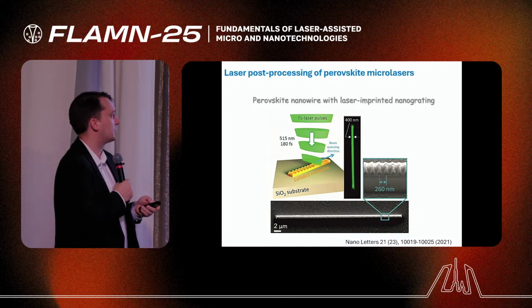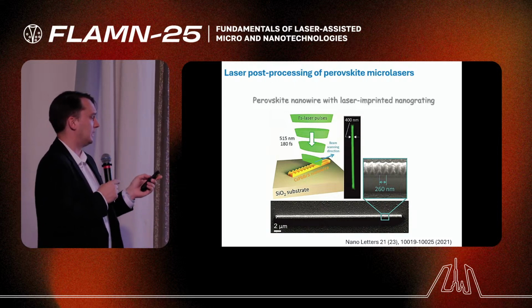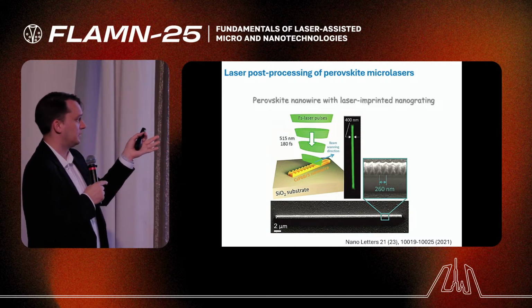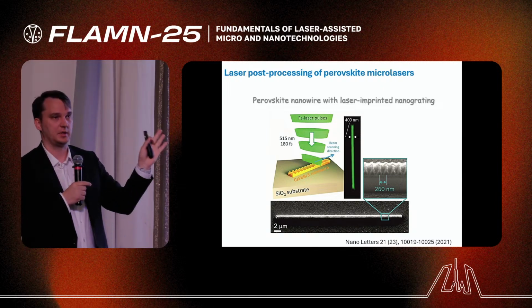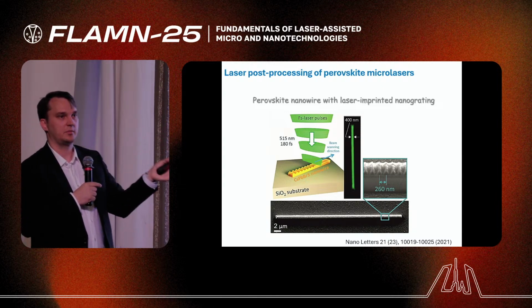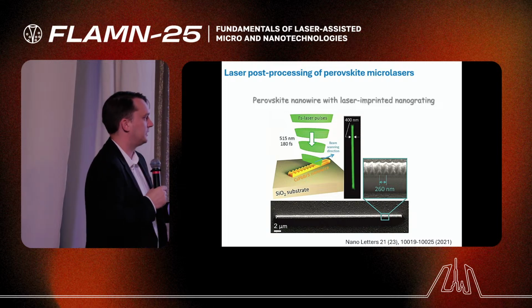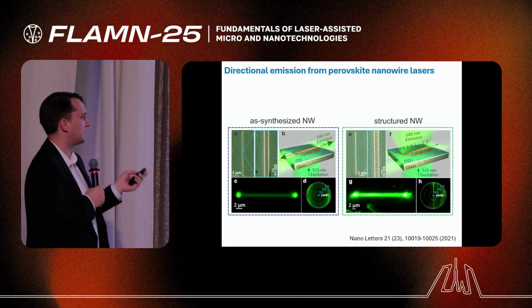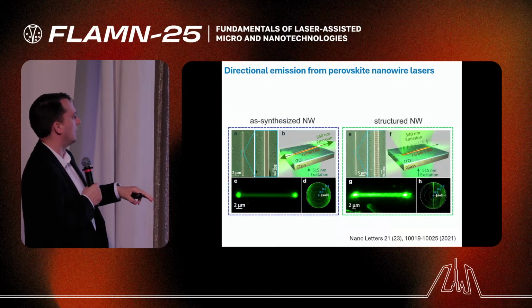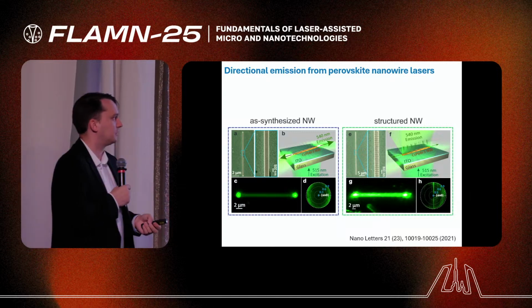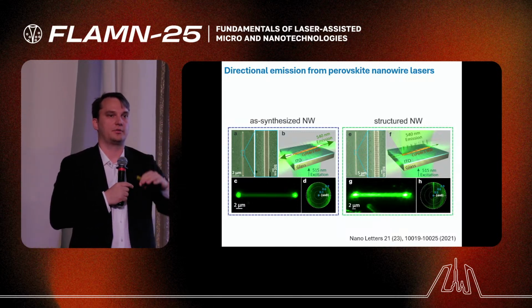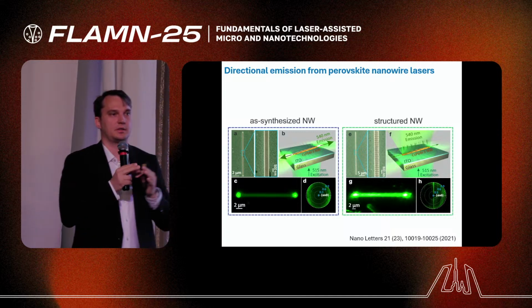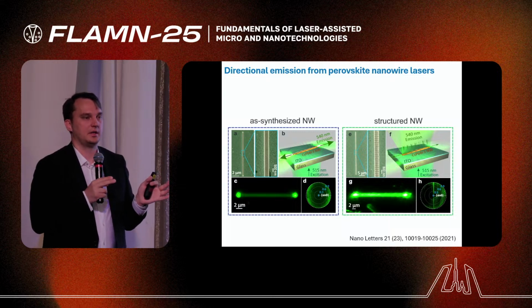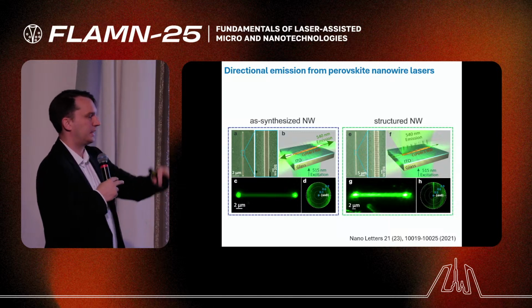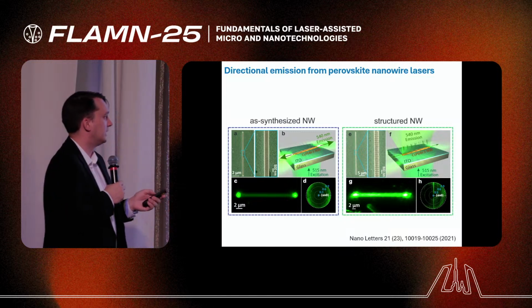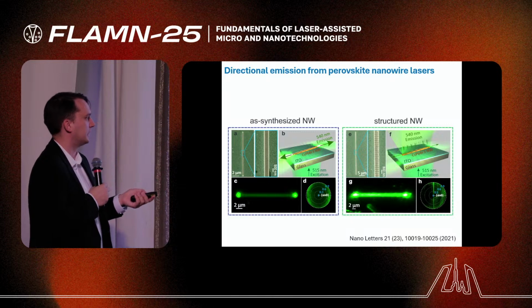And to avoid such situations, sometimes it's useful to use a fixed period. For this case, we synthesize perovskite nanowires and then apply a stripe laser beam to create a grating on top of it. Again, because of the high defect tolerance and low thermal conductivity of perovskite, we can expect that we don't destroy the other material under such a grating. This grating is useful for light outcoupling in the vertical direction from the nanowire, because usually perovskite nanowires work as a resonator and light emitting system, like a nanowire laser. But once we create a very shallow grating on top, we have leakage of light in the vertical direction. So that's how we can change and optimize the outcoupling of light from such a nanowire laser in the vertical direction.